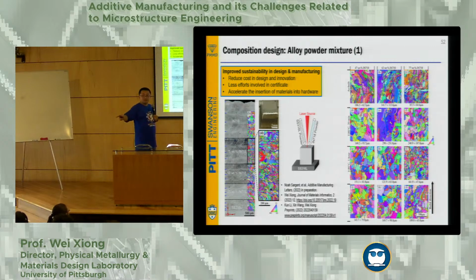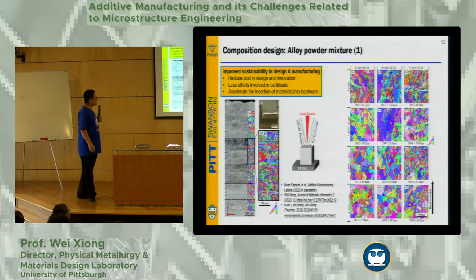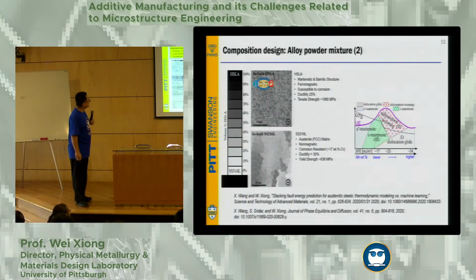As you can see the microstructure, which one is finer? If you don't have any issues with color, you'd agree this is a very fine structure. At 1180 degrees C, 1 hour, you still can see very fine structure. That's very encouraging, and this is a new material composition now.